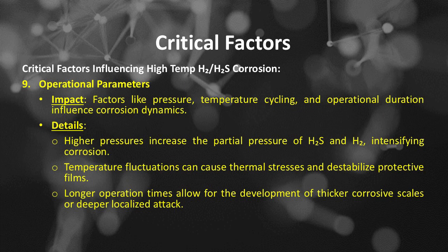Critical factors. Number 9 is operational parameters. The operational parameters impact: factors like pressure, temperature cycling, and operational duration influence corrosion dynamics. For details, higher pressures increase the partial pressure of hydrogen or H2 and hydrogen sulfide or H2S, intensifying corrosion. Temperature fluctuations can cause thermal stresses and destabilize protective films. Longer operation times allow for the development of thicker corrosive scales or deeper localized attack.